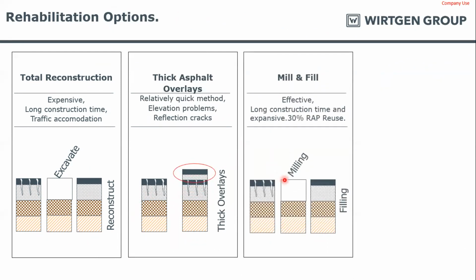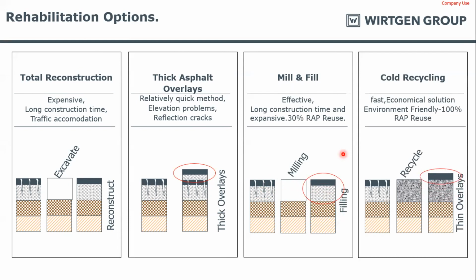The third option is mill and fill. We eliminate the existing cracks by milling with a milling machine, and then we can reuse the RAP back in the DBM layer. Here the code allows 30% RAP in DBM. The last option is CIPR. Depending upon the project economics and how much quantum of work you have, you can choose either mill and fill or CIPR. With CIPR you have the option of getting 100% RAP back into the system, so you get a faster construction of 1 lane kilometer per day. After the BSM layer, we lay a BC layer on top of it.